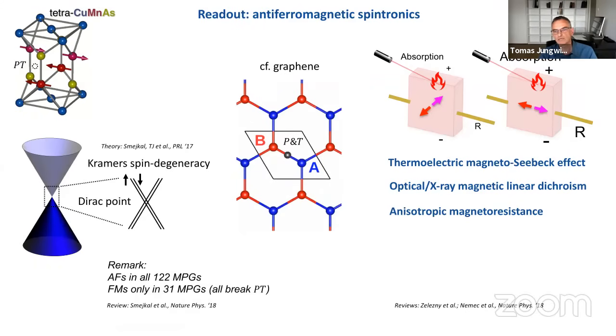Now, I mentioned already that one of the issues working with thin films is the weak electrical readout signals. So one way how to possibly get around this problem is to find singularities, if you want, in the topology of the electronic structure of these materials. And then due to this singular feature, one might also expect to find a singular behavior of the response, electrical response, including the anisotropic magnetoresistance.